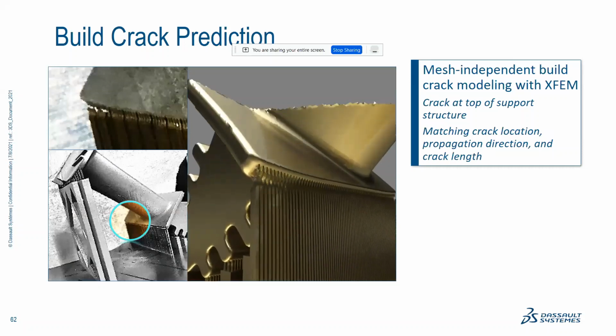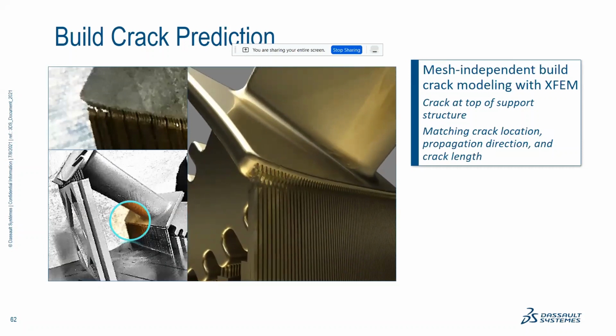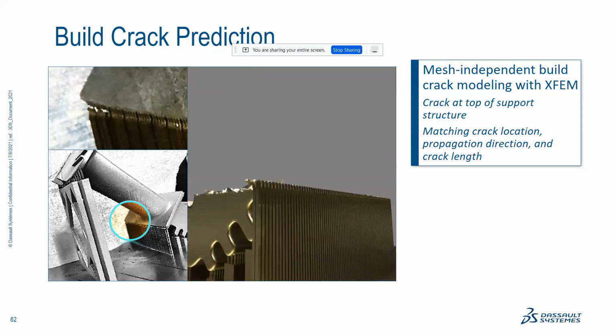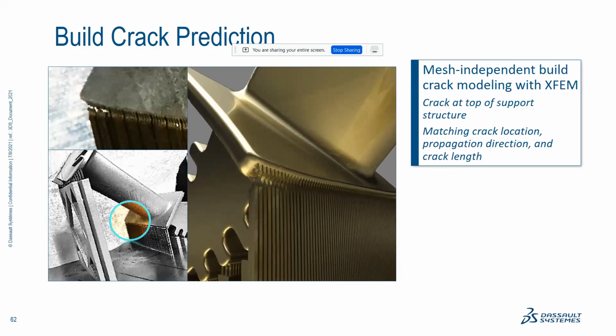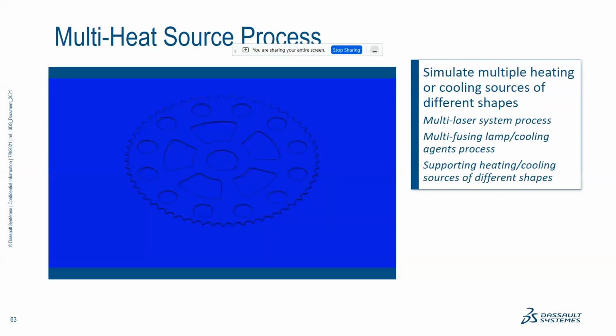To add on more value, so obviously failure is to be avoided. But unfortunately, any solidification process involves some form of a stress relieving phenomenon which causes these kind of cracks. So simulation is a very powerful tool. Based on a criteria framework, we can identify regions where crack is a potential initiator, and so we can have, like, say, stress-based criteria or strain-based criteria, and then we can basically predict the crack initiation propagation. We can also simulate multiple heating or cooling sources of different shapes through via multi-laser system.